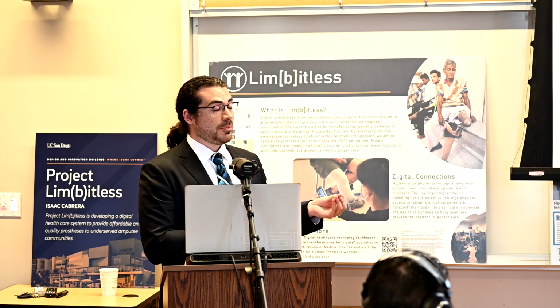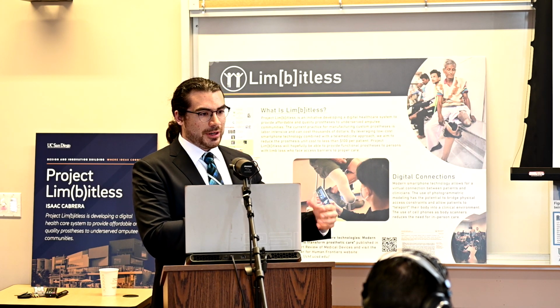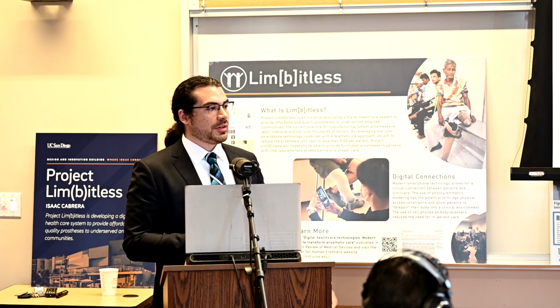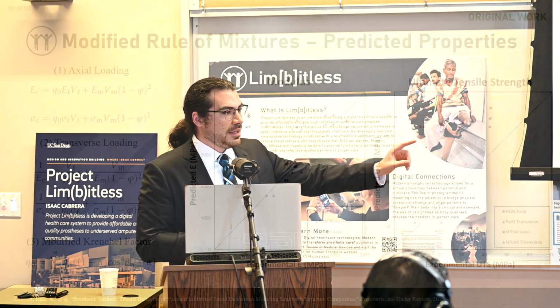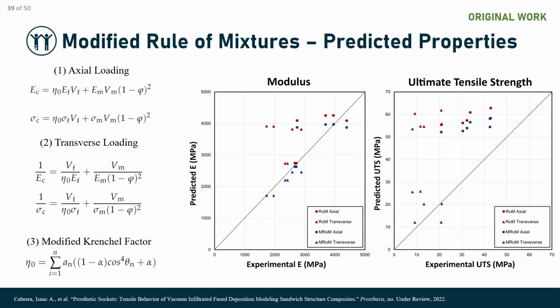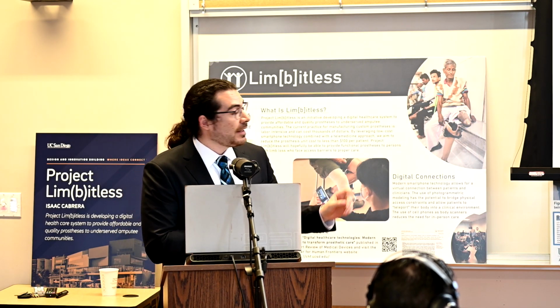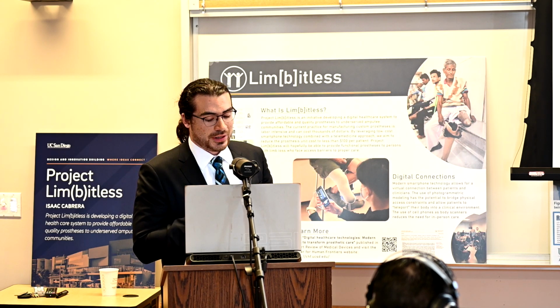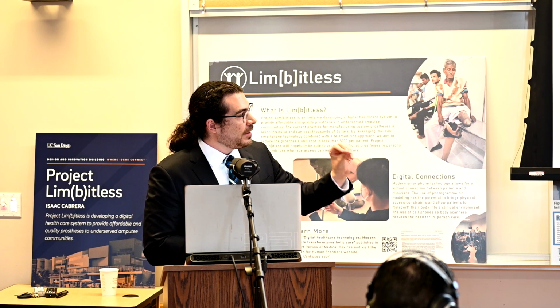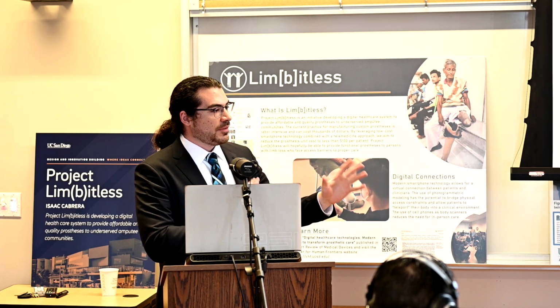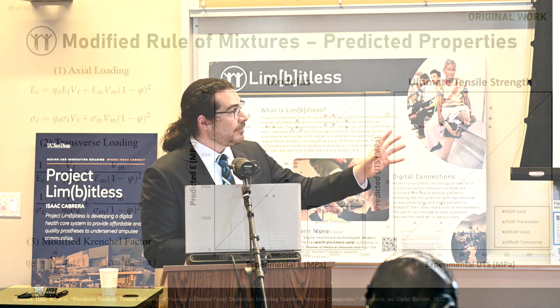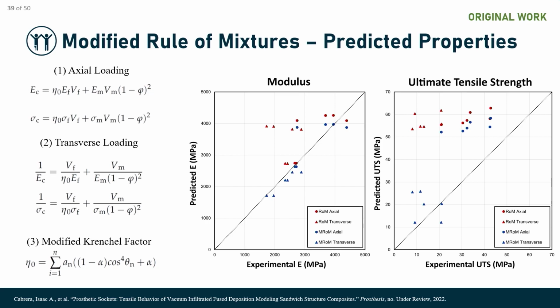and it was not just the properties of the matrix, and that's because our 3D printed filaments are basically continuous with each other. And so I added this factor, which is the A sub n, which is just a bound. It basically bounds it so that you can never get lower than the transverse properties. So by simply measuring or predicting the degree of anisotropy, you can predict the strength of that filament material. Finally, on the right-hand side, we see the ultimate tensile strength. I was pretty happy that I was able to improve the transverse material strength prediction, but still for the axial, it's still a bit off. You can see that it's still, of course, just an approximation.